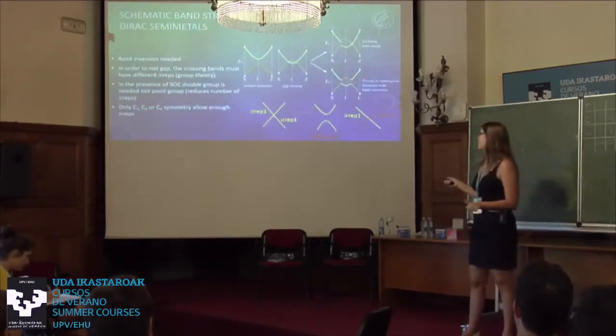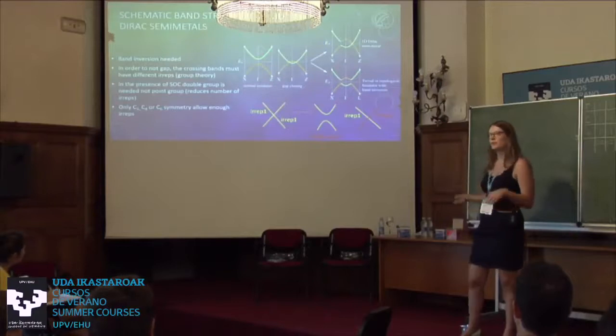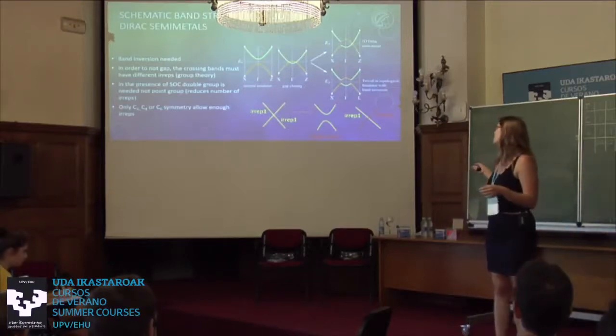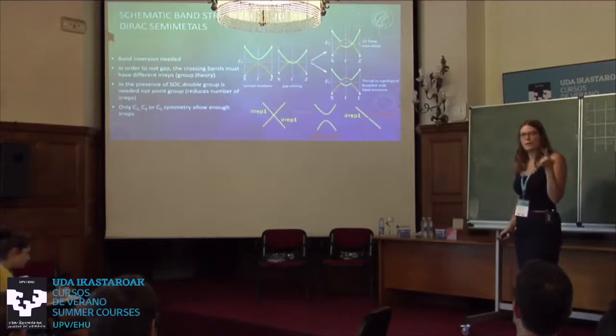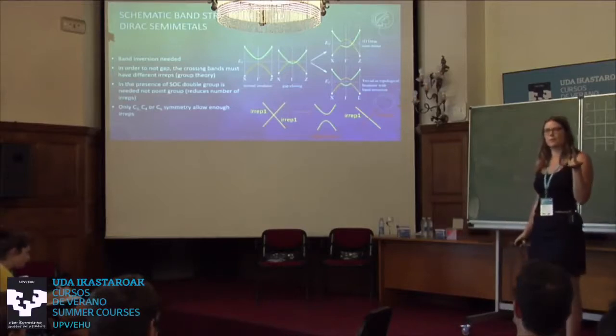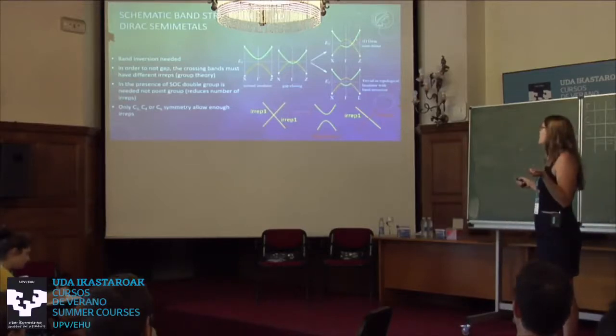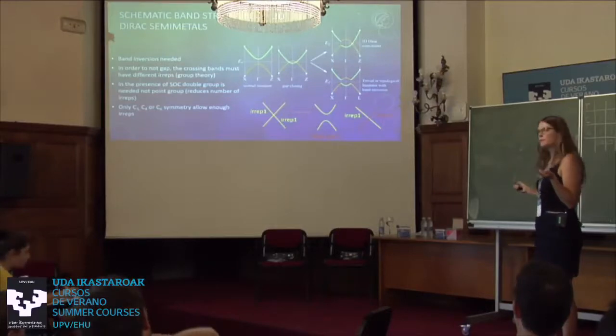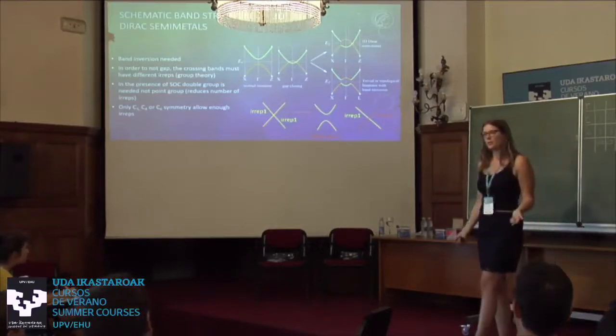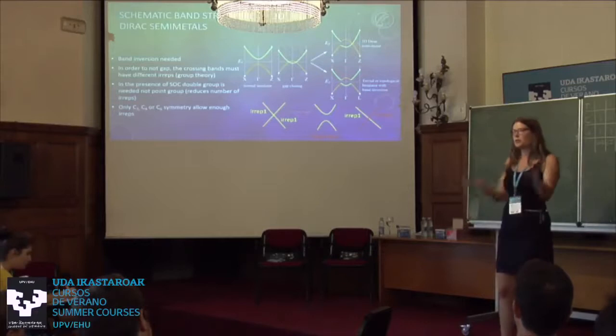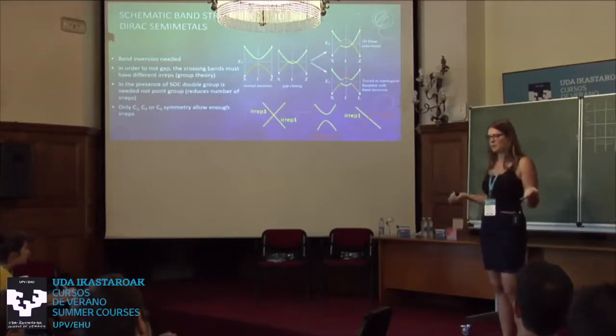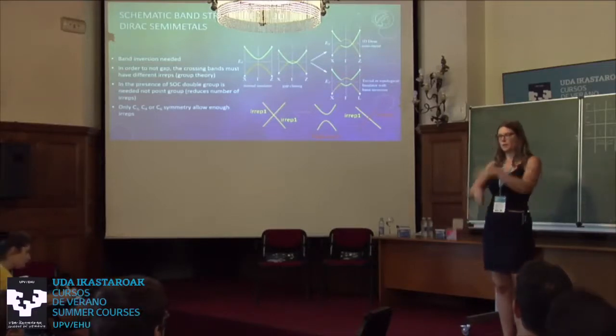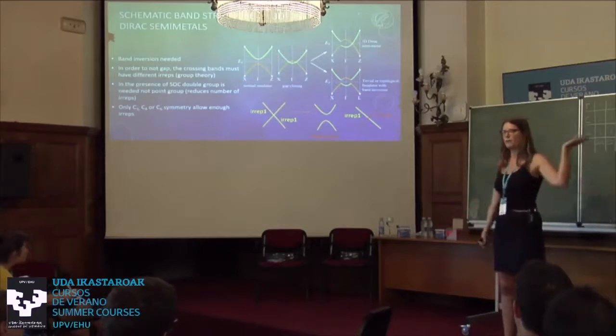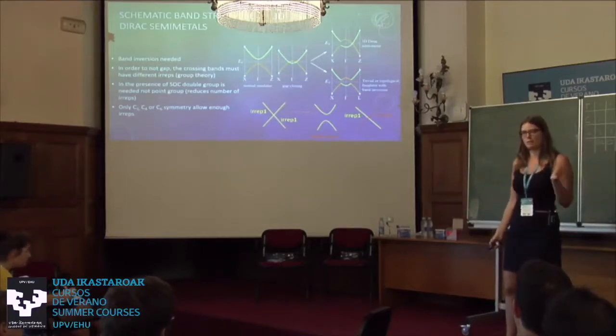Then this is a charge balanced band structure. We started this process here from a charge balanced compound. So we want to have the correct electron counts. We want to look for a charge balanced material. And then we want to have a zero density of states here. We just want to have the Dirac crossing there. So we need to have somehow a good ratio between electronegativity difference and spin-orbit coupling so that we don't have a metallic compound, but we also don't have a wide band gap insulator where we would never have a band inversion.